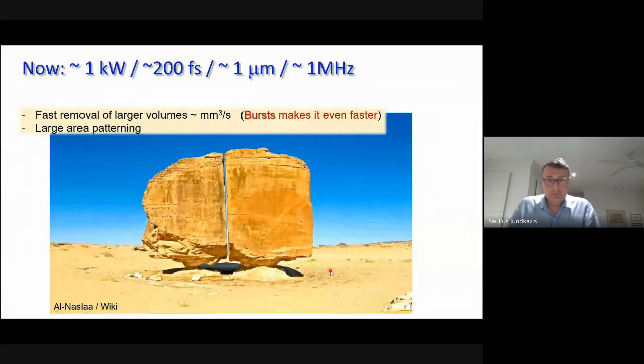So now it's not a serious slide, but look at this. It's giving the message that now with kilowatt ultrashort lasers at high repetition rate, we can really begin to think about fast removal of large volumes. We are speaking about cubic millimeters per second, and the burst mode of femtosecond lasers, which usually is a current trend, can help us.